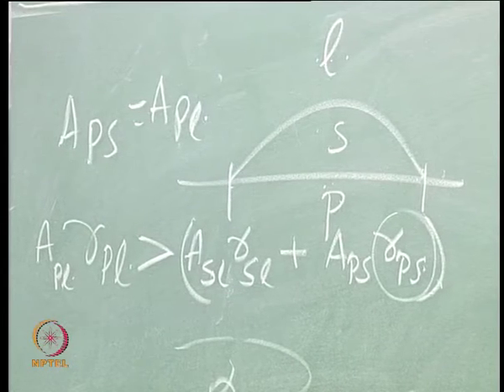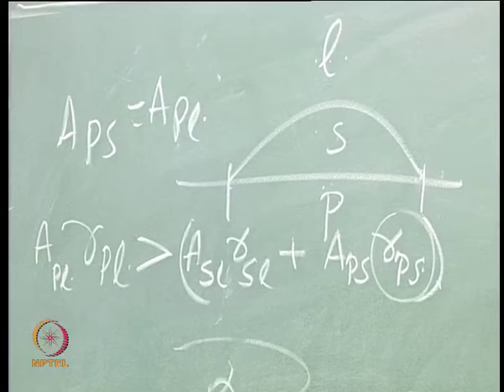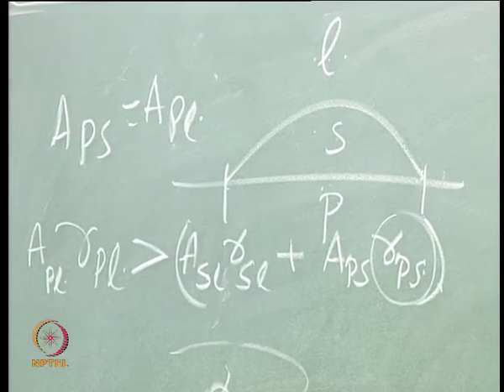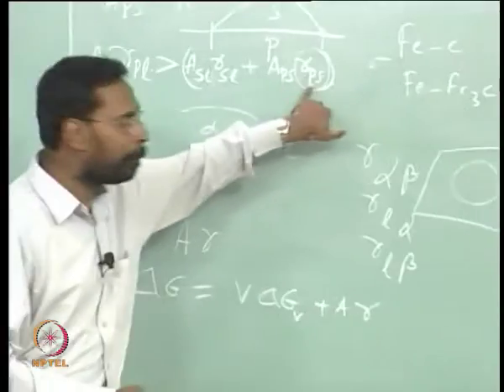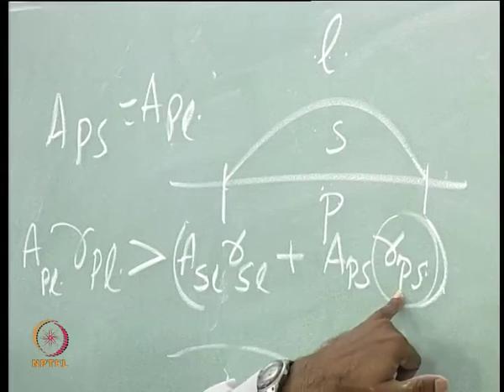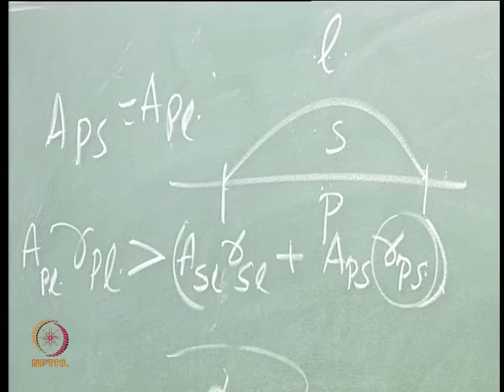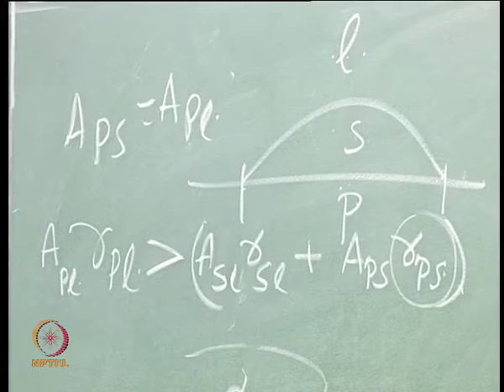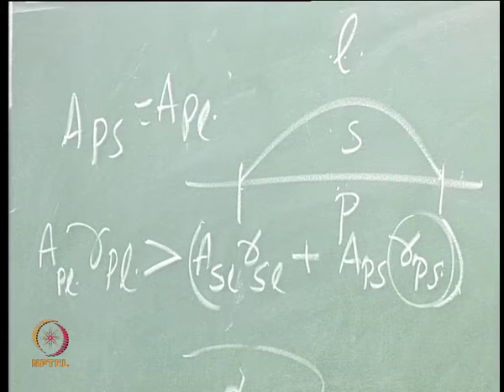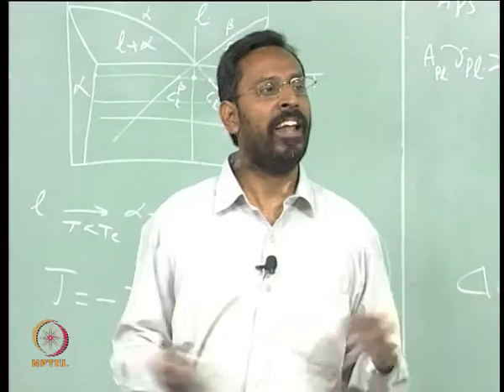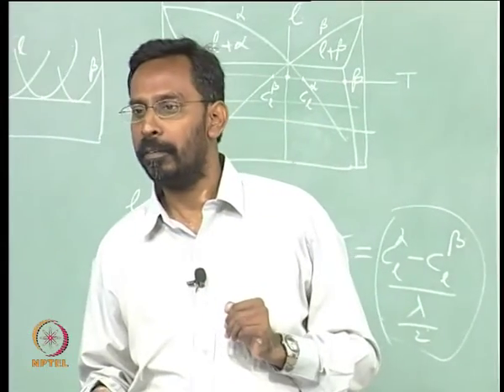Gamma SL is between liquid and solid, that has nothing to do with which particle I have added, but gamma PS is decided by the structural compatibility between the solid and particle. Whenever the particle has a very similar structure, that is a good nucleating site - that is why when I take an aluminum alloy and add a TiB2 particle, it acts as a good nucleating site.